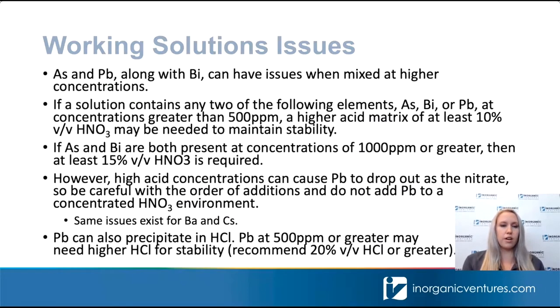Another issue that can occur happens when you have a combination of arsenic, lead, and bismuth at high concentrations. So if you have any two of these three elements at concentrations greater than 500 ppm, you may need to increase your nitric acid concentration to at least 10% to prevent any type of precipitate from forming or instability issues. For arsenic and bismuth especially, if you have high concentrations of 1,000 ppm or more, you definitely are going to need to increase that nitric even more to about 15%.